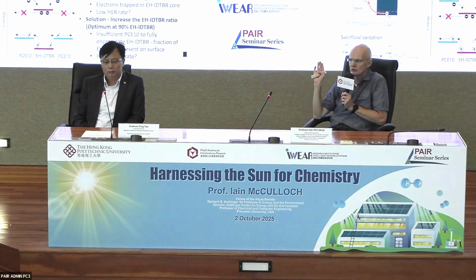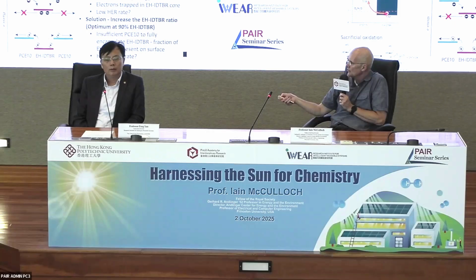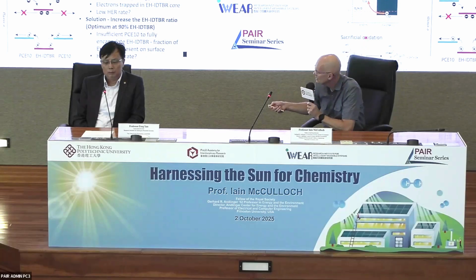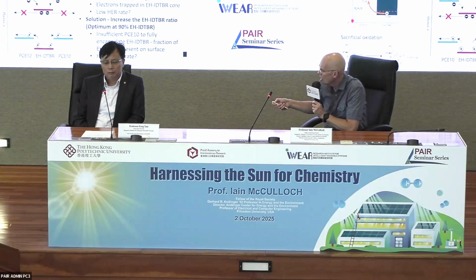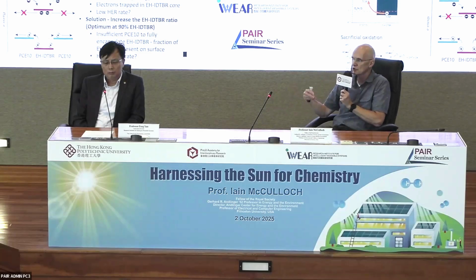So only now are we starting to develop structure-property relationships around these materials. What we're finding is it's quite easy to have a material, so this is the heterojunction, right? If the hole is down here, then theoretically it can oxidize water, but you need about a 0.4 to 0.5 overpotential. So you need a HOMO energy level of almost 6 electron volts, which is hard to measure by UPS because it's so deep. You need a very deep HOMO, and then a co-catalyst like cobalt, and a reduction catalyst, some sort of silver catalyst or whatever, all in combination. So it's not straightforward, but it's definitely doable, and we've been working on that now.